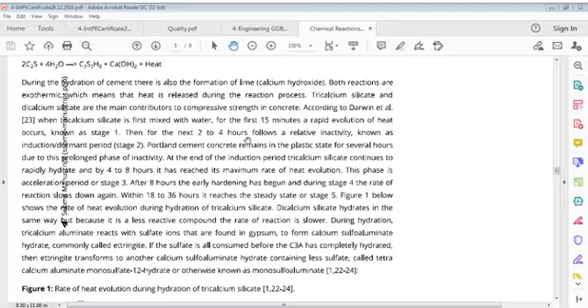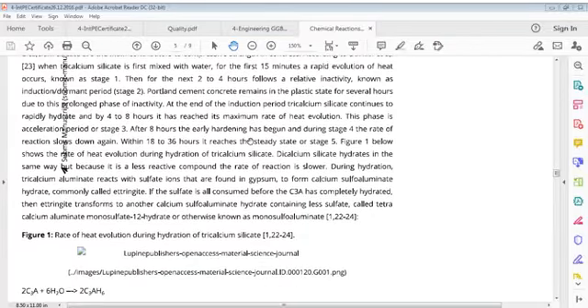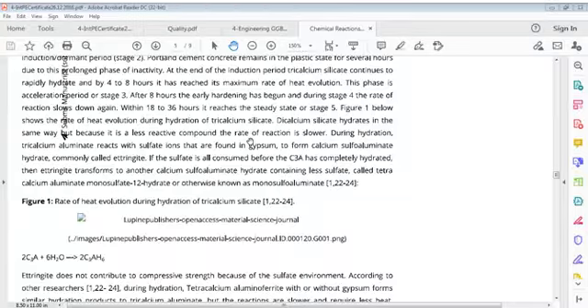it reaches its maximum rate of heat evolution. This phase is the acceleration period of stage 3, that is 4 to 8 hours, when it reaches the maximum rate of heat evolution. After 8 hours, early hardening has begun, and during stage 4 the rate of reaction slows down again. Within 18 to 36 hours, it reaches its steady state of stage 5. The figure below shows the rate of heat evolution.